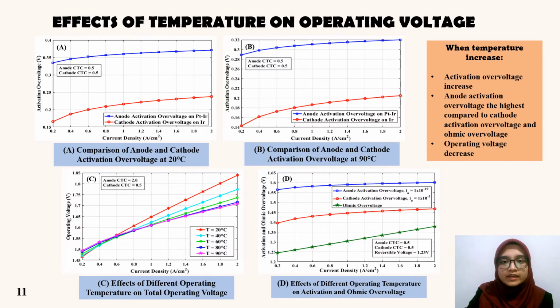Next is the comparison of anode activation overvoltage and cathode activation overvoltage that was made on the lowest and highest temperature, which is 20 degrees Celsius and 90 degrees Celsius, that can be seen on figure A and figure B. So it can be observed that the value of anode activation overvoltage is higher compared to cathode activation overvoltage. This is because the energy required to initiate the electrokinetic process at the anode is higher than at the cathode. The anode electrode requires more energy, which is used to split water into hydrogen gas and oxygen gas. While at the cathode side, the hydrogen ion and the charge of electron is already reacted without requiring any external influence. So that is why less energy is needed at this side of the electrode.